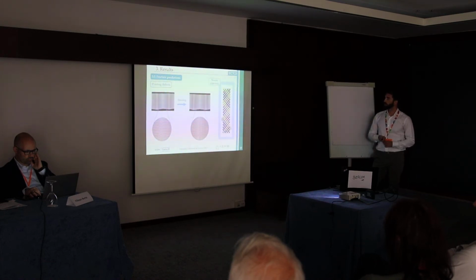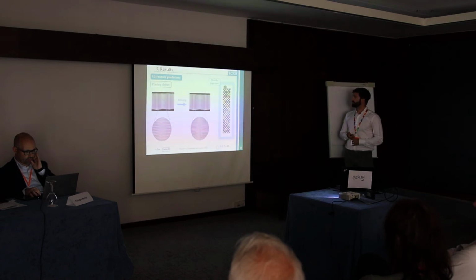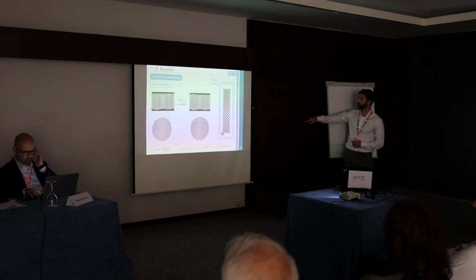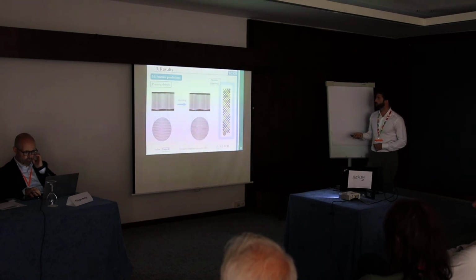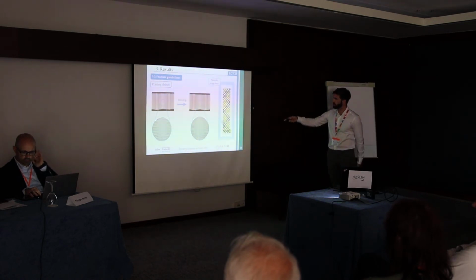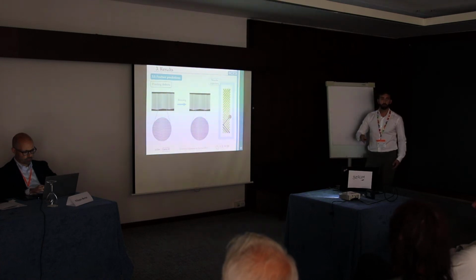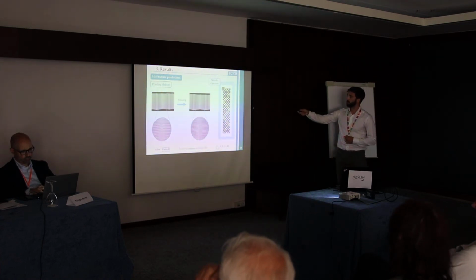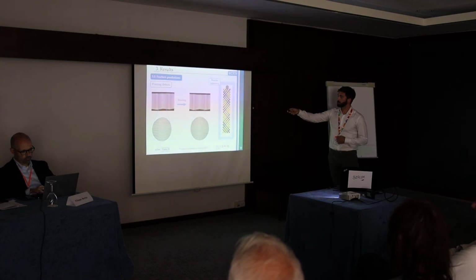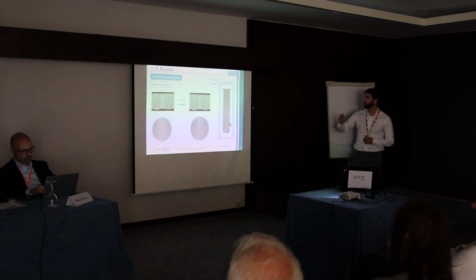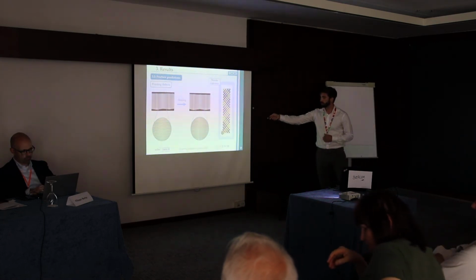Okay, now what we conclude from this is that the microplasticity necks that I mentioned before are generated because of the grid pattern. On the right you have the nozzle trajectory to complete just one line, and we can see that the nozzle passes through each joint 2 times. So this generates accumulation of material. On the left, you have the overlapped filaments before the bending, which reduce the diameter of each filament,